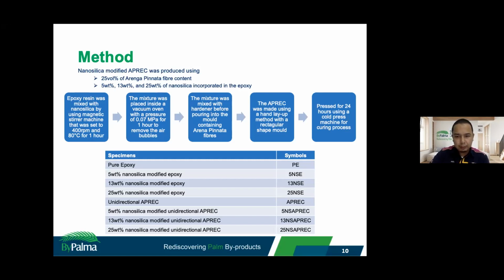Then the APREC was made using the hand layup method with a rectangular shape mold. And then finally, the specimens were pressed for 24 hours using a cold press machine for the curing process. And then these are all the specimens fabricated in this project.